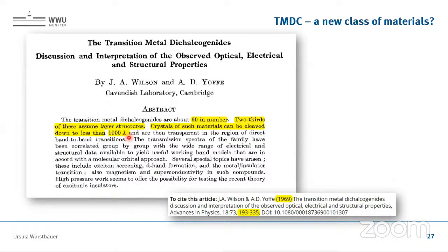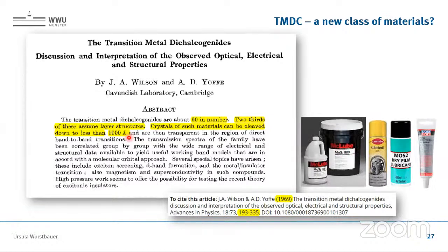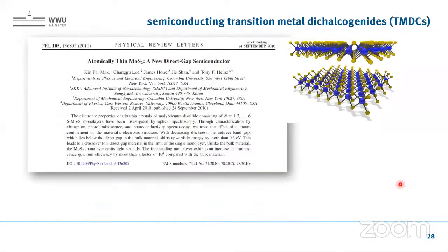But still, for some properties it's worth having a look at this old literature, because a lot of it was already known, and we do not need to reinvent the wheel. We can go back and see what is already known on those materials. Actually, it's not only known for the electronic and optical properties. Those materials are also known as dry lubricants. Maybe in the morning if you ride a bicycle, you will have a compound with some of those van der Waals materials, either molybdenum disulfide, a naturally occurring transition metal dichalcogenide, or graphite, where the layers smear off and it's a perfect dry grease in that sense. However, let's now go back to the optical and electronic properties.